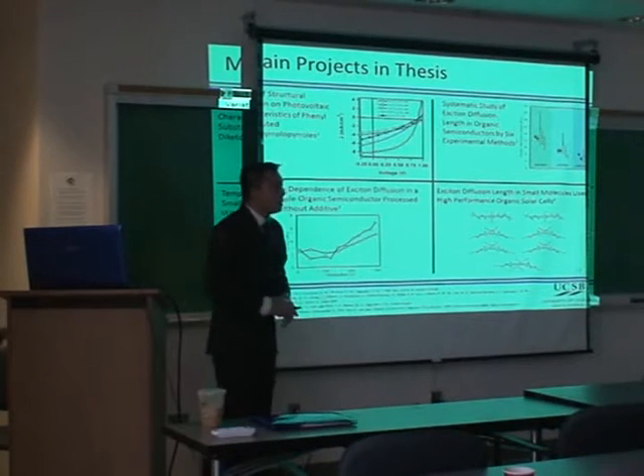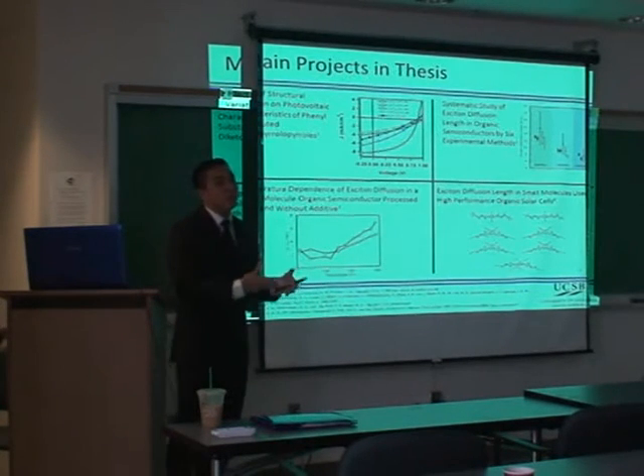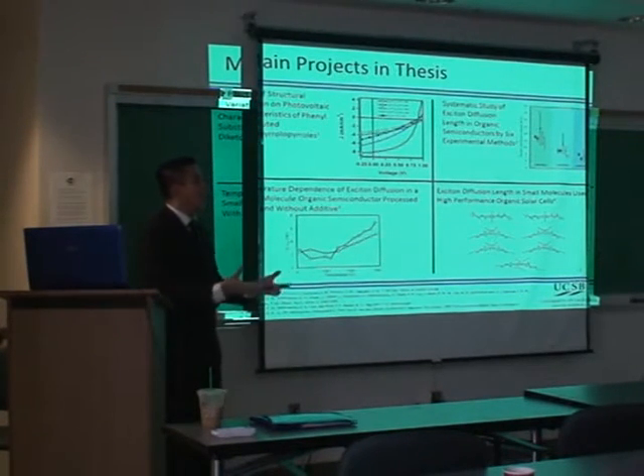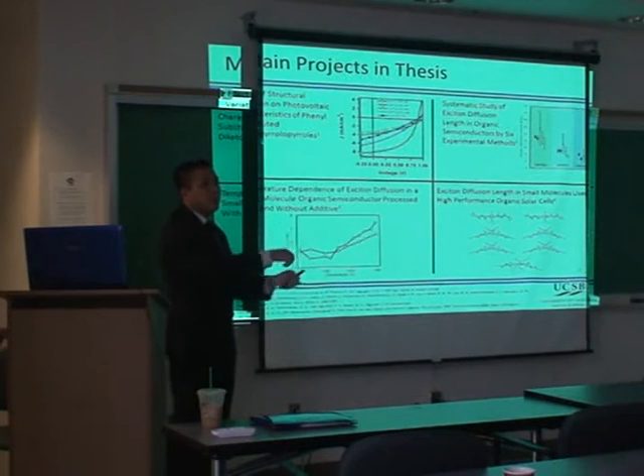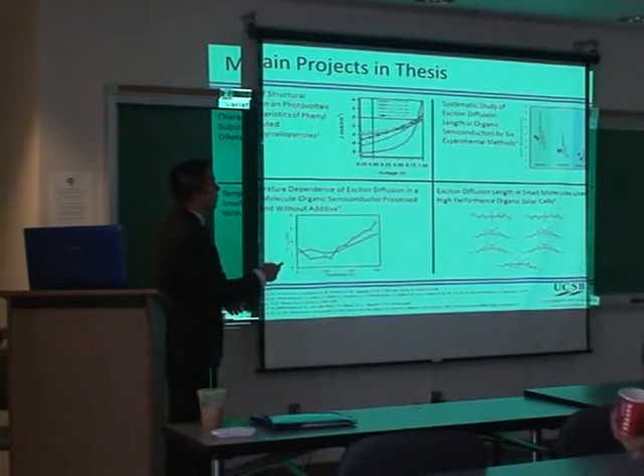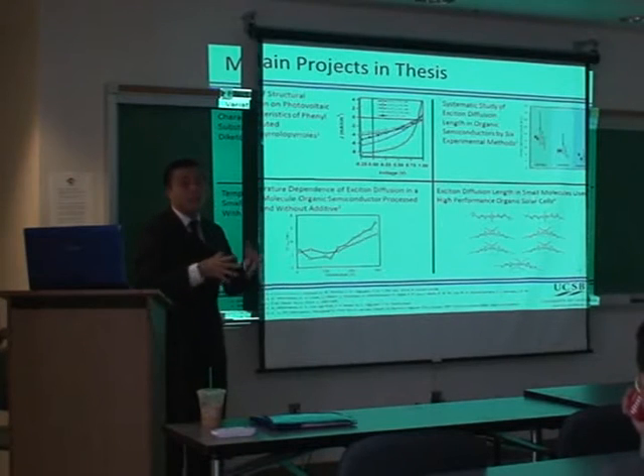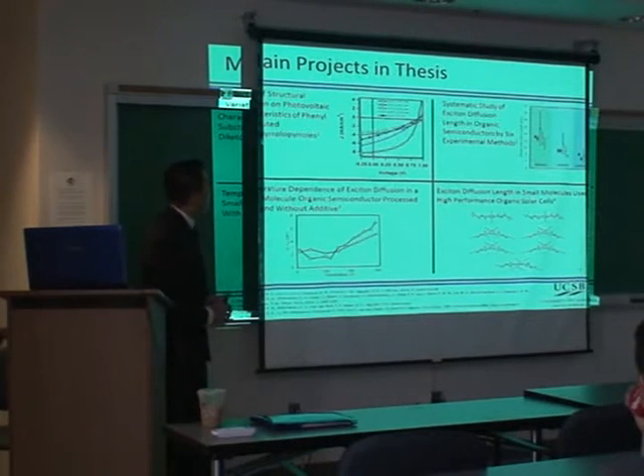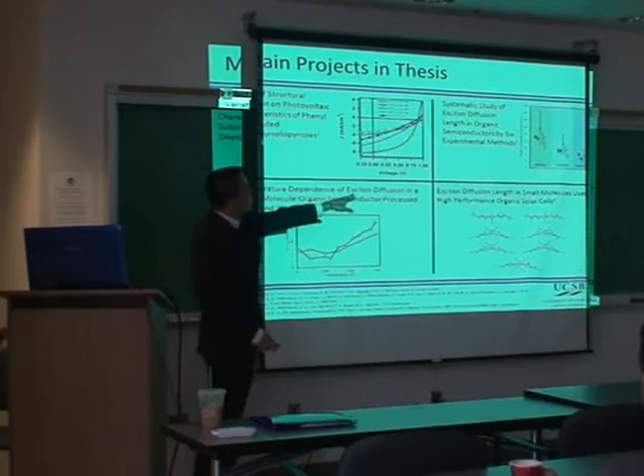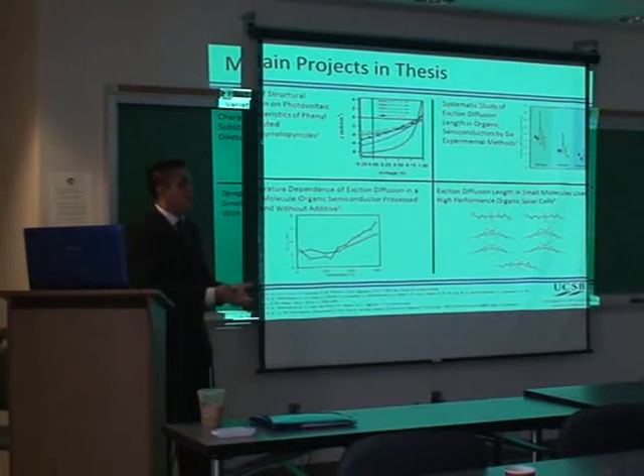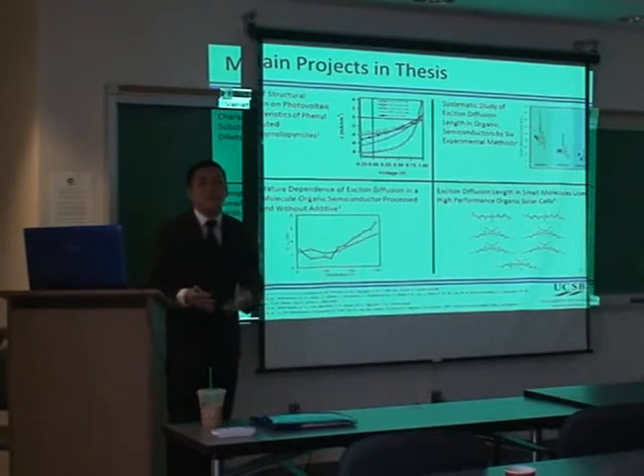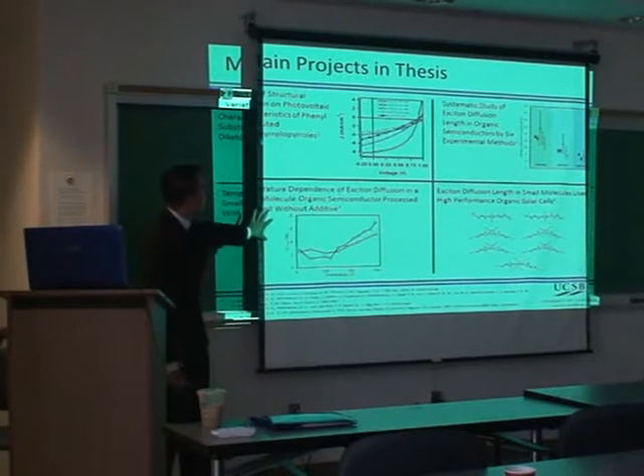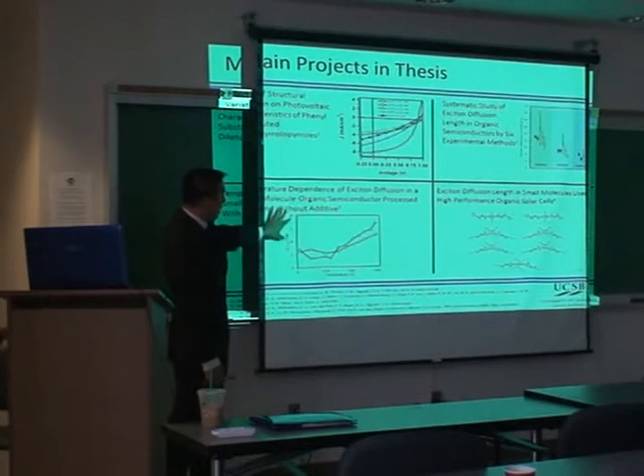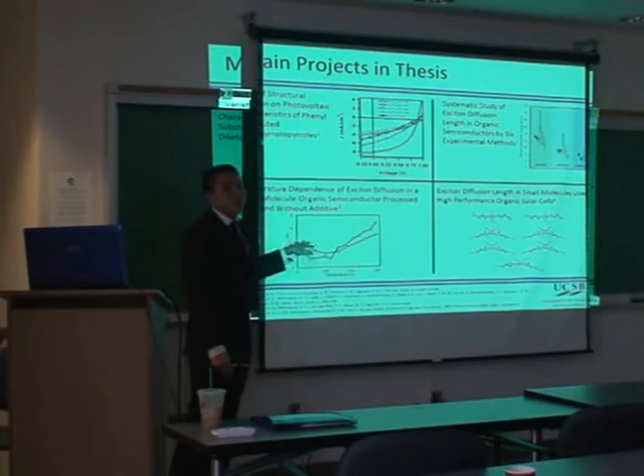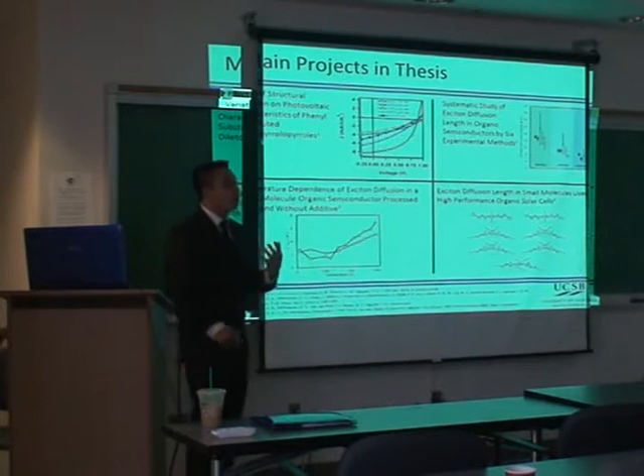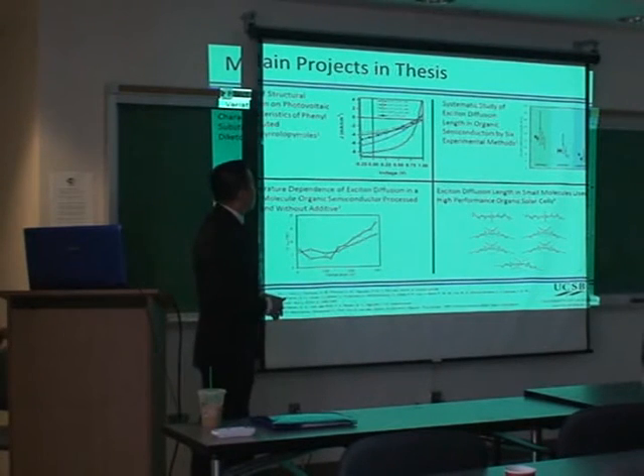What I then did is I used some of those same molecules for my next project, project 2, which was to study how these same chemical modifications impact fundamental properties like the exciton diffusion length. In addition, I wanted to compare different techniques to measure exciton diffusion length, because there's many different techniques, as I will elaborate later. And then after that project, I wanted to delve deeper into exciton diffusion length, like what is actually the mechanism of exciton diffusion. So in this project, I used temperature studies, and I measured the exciton diffusion length at different temperatures. In addition, I wanted to look at how processing condition affects the exciton diffusion length.